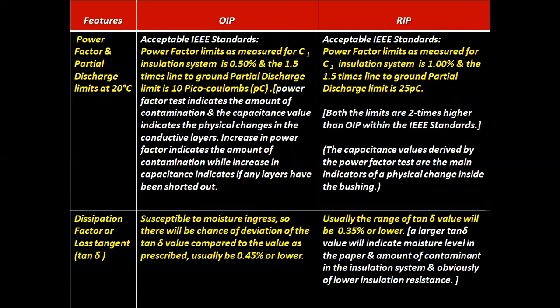Power factor and partial discharge limits at 20 degrees centigrade. Acceptable IEEE standards: power factor limit as measured for the C1 insulation system is 0.50%, and the 1.5 times line to ground partial discharge limit is 10 picocoulombs. The power factor test indicates the amount of contamination, and the capacitance value indicates the physical changes in the conductive layers. An increase in power factor indicates the amount of contamination, while an increase in capacitance indicates if any layers have been shorted out.